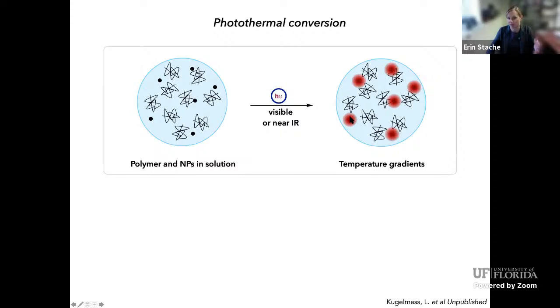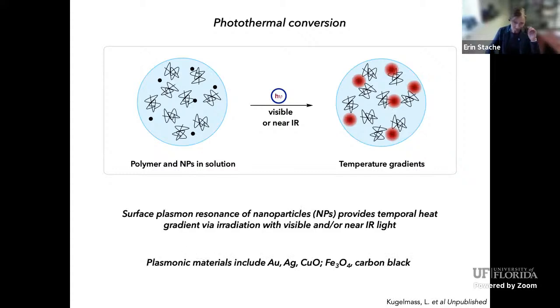And so you'll get really, really hot temperatures right around the surface of the particle, but the bulk solution itself will stay around room temperature or slightly higher. And so if these temperature gradients interact with a polymer, you can imagine that you can start breaking bonds in the backbone of the polymer.